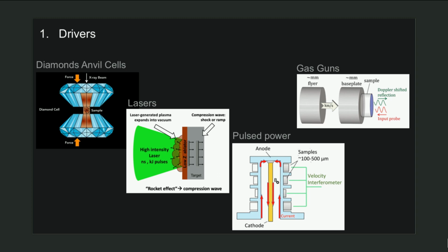And so a lot of the ways that we try to design experiments is all dependent on when materials shock up. As materials go to higher pressure, their inherent sound speeds are faster as well. And so every wavelet traveling behind the front wave is moving at a faster speed, and so they coalesce. It's very easy to coalesce and become a shock wave. And so with ramp compression, you try to take advantage of the fact that some materials are strong and you won't have as much of a coalescence. And so there's different ways to play around with the loading shape.